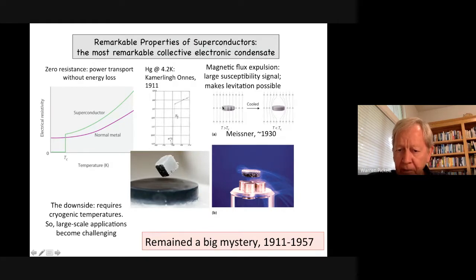It's not shown here, but what they do is there are vortices left in the material in which the magnetic field goes through the superconductor, and at the center of the vortex, the material is actually normal, but the whole material as a whole is superconducting, and still the resistance is zero. So here's another levitation, the magnet over probably an yttrium barium copper oxide, a superconductor cooled below 70 degrees, which is enough.